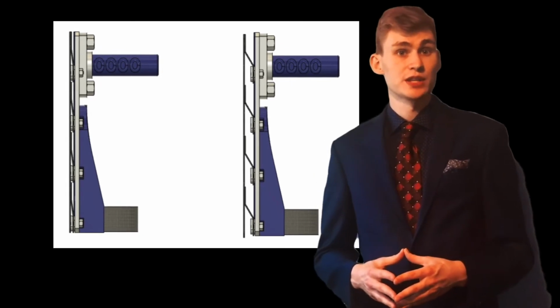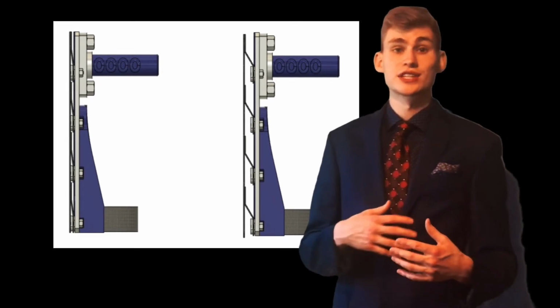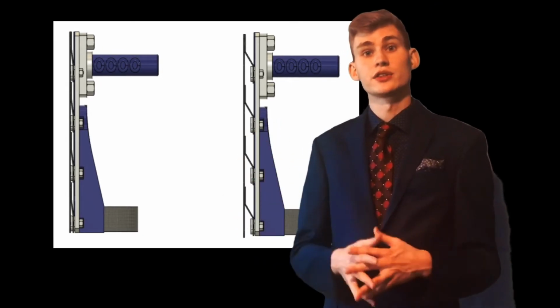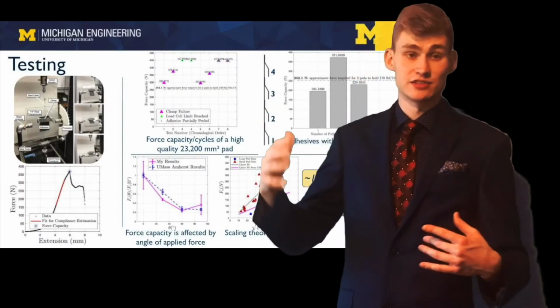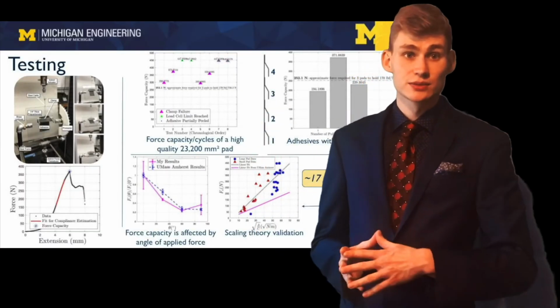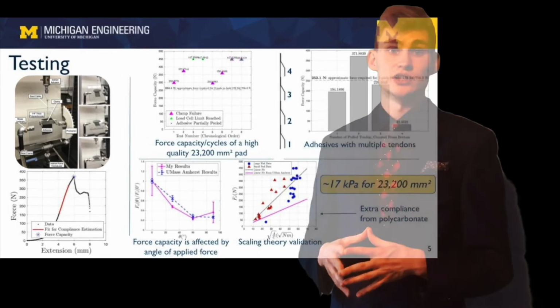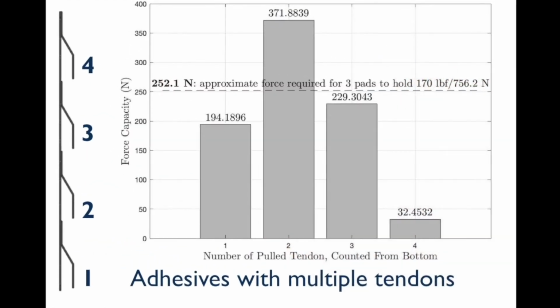My initial design for the climbing paddle used 4 tendons placed periodically throughout the height of the pad in order to keep the pad oriented about parallel to the climbing paddle, which would aid in adhesive placement. So my next test was to examine how the force capacity changes when you're loading different tendons. I found that loading the tendon closest to the center led to the highest critical load of about 371 newtons, while loading the tendon highest on the adhesive led to a significantly lower critical load of about 30 newtons, presumably because the adhesive begins to peel.